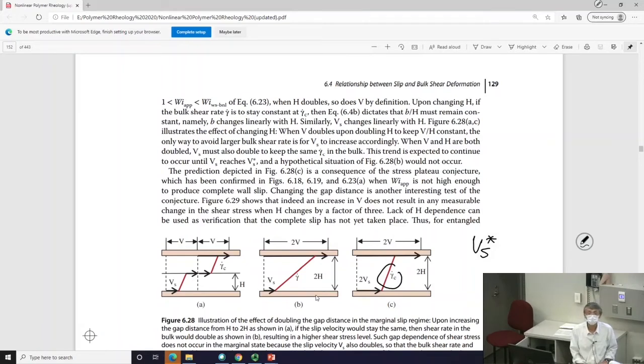What does this mean? If I can extrapolate, this B will be twice of that B by definition. And 2B over 2H will be the same as 1B over 1H. In other words, as I increase my H, my B also proportionally increases. It's not magic. I mean, it's all completely understandable.